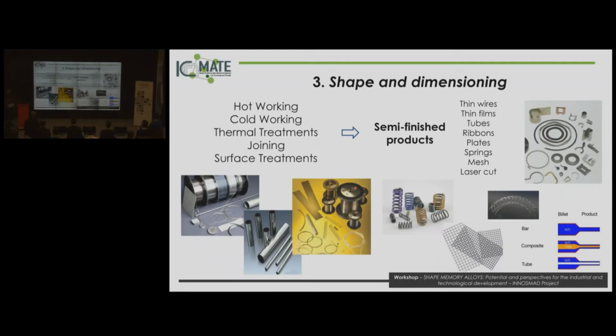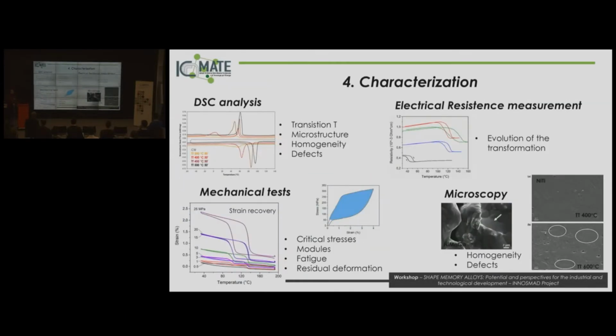As I said before, we can obtain a lot of different semi-finished products with all these processing techniques, and among them, for nickel titanium in particular, we can obtain thin wires, thin films, tubes, ribbons, plates, and, important for the SMA project, springs, meshes, and finally we can also apply the laser cut to nickel titanium components, as is used for the stents, for example. And finally, the fourth step, very important, is the characterization.